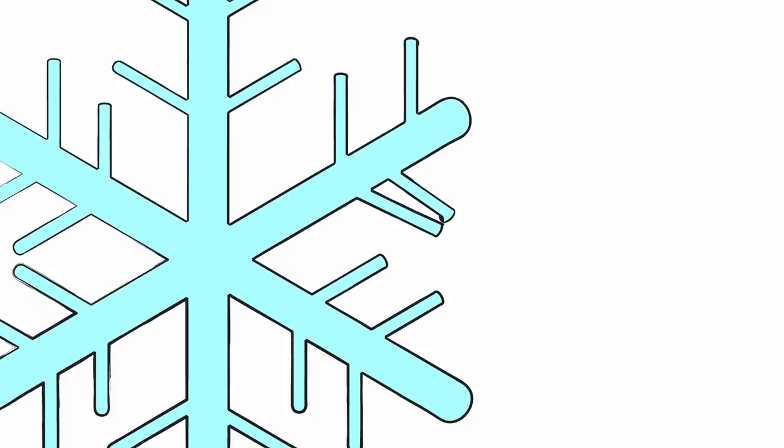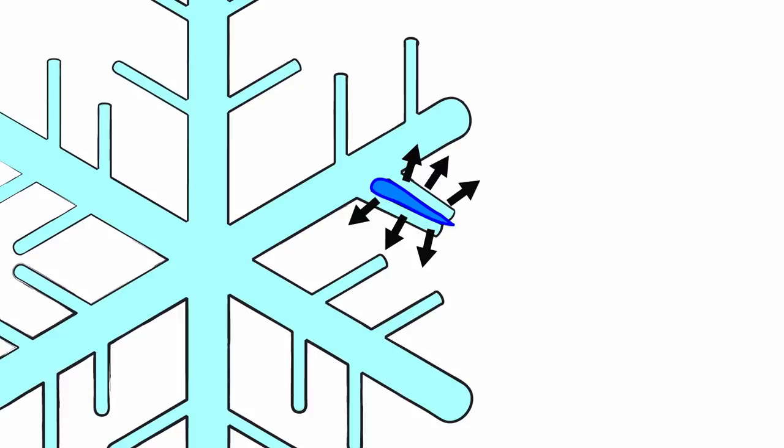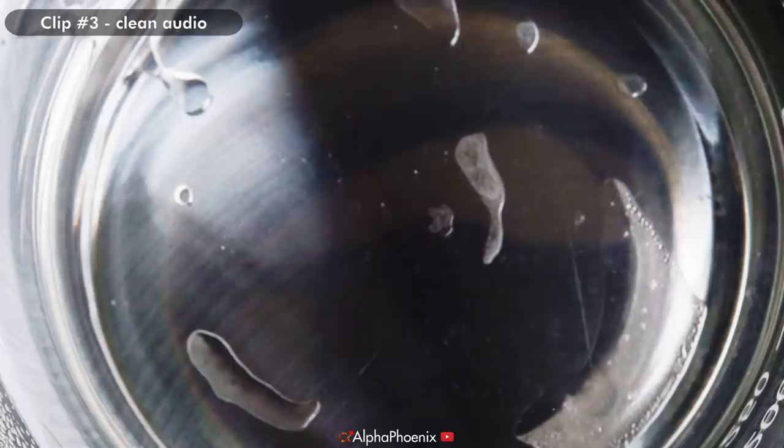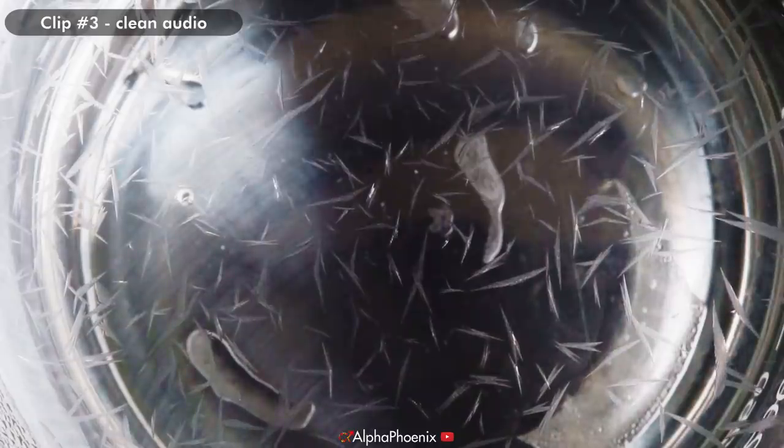In the case of water, the weakening and cracking of the structure I think are actually performed by the same mechanism — expansion. Water, unlike metals, actually gets bigger when you freeze it. A certain volume of liquid water gets about 9% bigger when it turns into solid water, and 9% is a huge difference. When you're talking about how much you can flex a material before it cracks, very few things can stretch 9%. That means that every time two dendrite arms trap a bubble of water, that liquid water doesn't actually have room to freeze — as it solidifies it wants to take up more and more space, increasing the pressure inside its little pocket and pushing out on the surrounding ice until it cracks. When you have hundreds of dendrites growing out of a bunch of nuclei across the surface of water, you can end up trapping a lot of little bubbles and causing a lot of loud cracks.